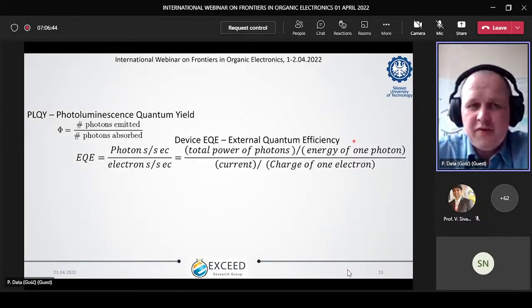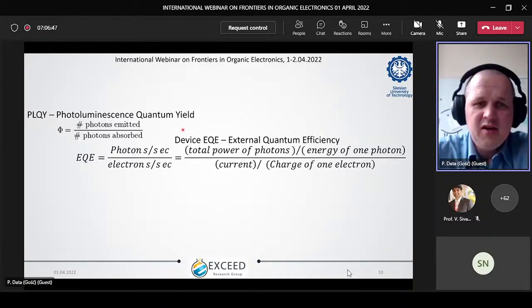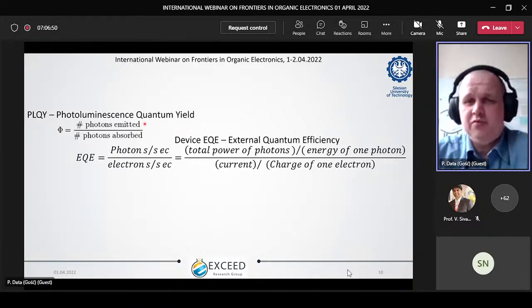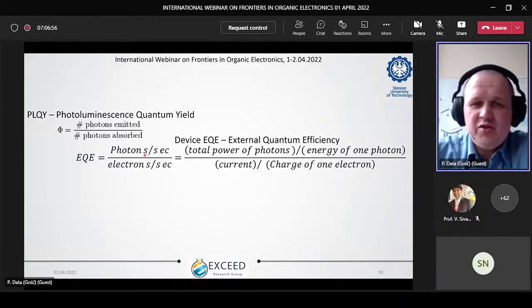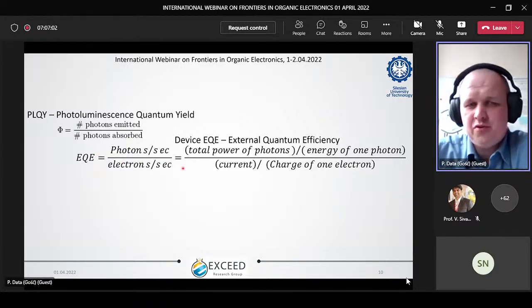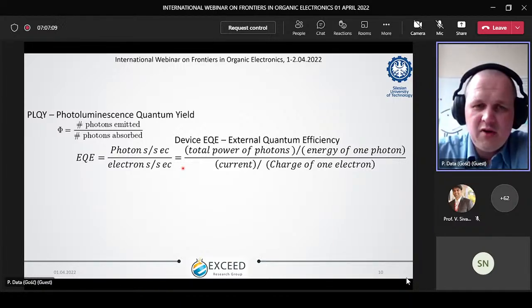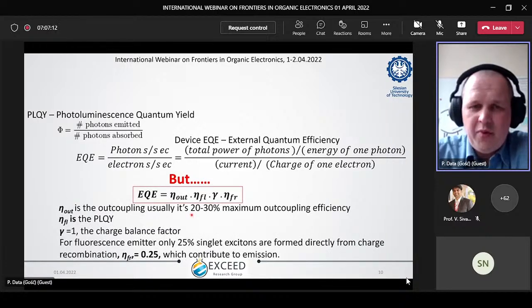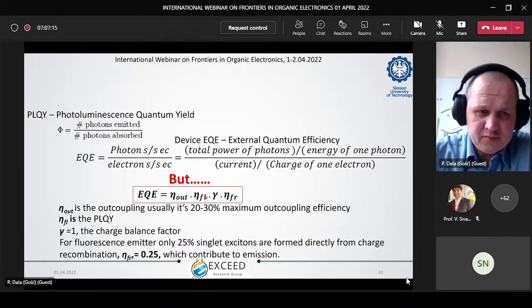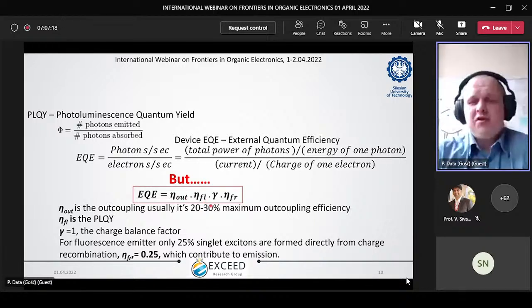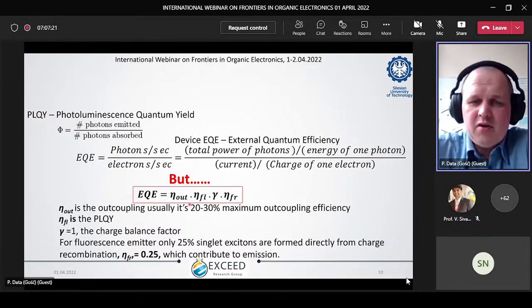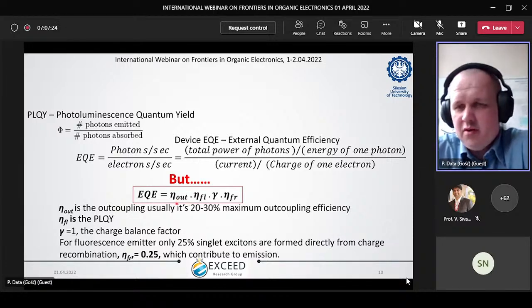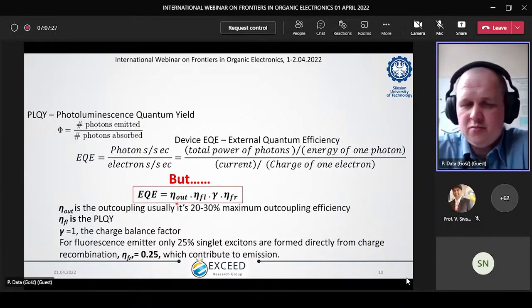So the amount of photons emitted, if you see here, to those absorbed. If you think about devices, OLED devices, our parameter is external quantum efficiency, which means how many photons we generated and how many electrons we push into our devices. And there is a really nice equation which previously Ken showed us, where we can combine our EQE and our PLQY of our emissions. So we use this equation to screen our materials quite fast to know if our organic emitter will be efficient in the form of the OLEDs.